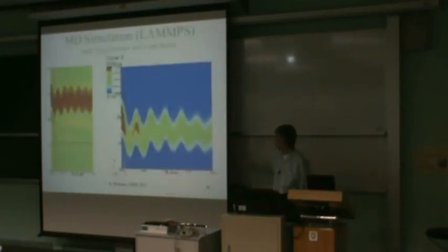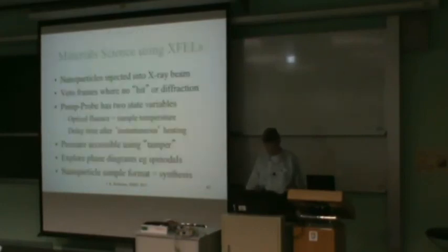Okay, here is a simulation of a heat pulse coming into a generic crystal, and you can see the waves of vibration traveling through it. And if you take that MD simulation and Fourier transform it, you get a nice oscillation of the Bragg peak position. Okay, so I'm going to stop at this point and skip forward to